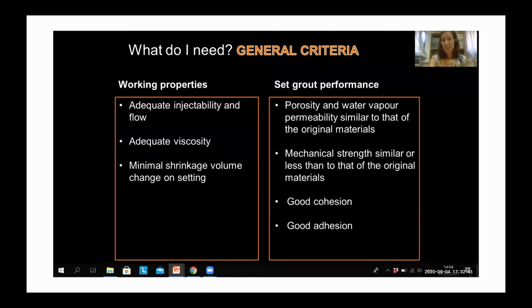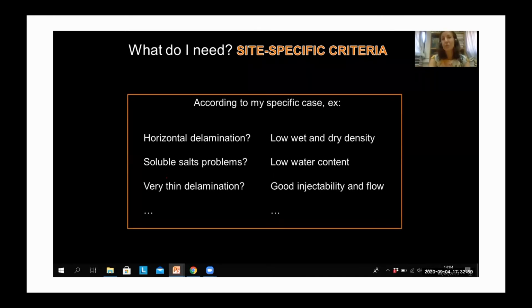So general criteria for every grout, but as I said before, of course, we also need site-specific criteria. What does site-specific mean? They tackle the specific problem we are facing in that particular site. So for instance, do I have a horizontal delamination? In that case, very likely I will need some light material, so something having low wet and dry density. Or do I have a particularly severe problem with soluble salts? There is a high contamination of soluble salts. I will need, for instance, a low water content in my grout.